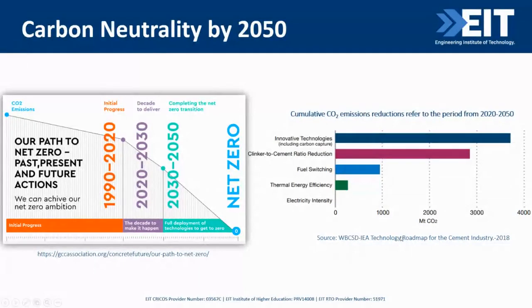On the right-hand side, we can see carbon emission reduction of about 50% by innovative technology, including carbon capture, and roughly 40% by reduction of the clinker to cement ratio. So both of these ways lead in cumulative carbon dioxide emissions reduction in cement making, in cement production. Their contribution, these two jointly, is equivalent to almost 80% of current global direct carbon dioxide emissions from the total industrial sector.